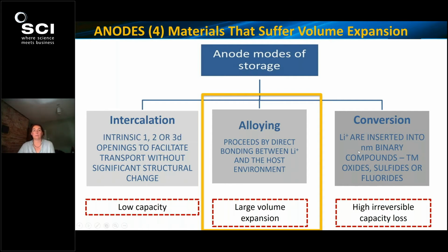So then moving to the central group or central mode of lithium insertion, these are elements that alloy with lithium, and these can be metalloids such as silicon or metals such as tin. And the alloying mechanism proceeds by directly bonding between lithium and the host environment. And so the crystalline structures of these materials become amorphous as the lithium inserts itself. Unfortunately, this results in an enormous volume expansion of the material because they can accommodate much more lithium, which is why they can represent a much higher specific capacity. But again, it's always a balance between how much you charge these materials with how much damage you then see within electrodes, because not all electrode structures can accommodate such large volume expansion from the active materials.